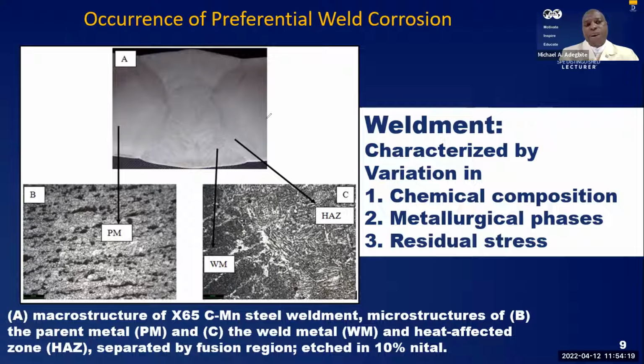You appreciate that the cooling is so sudden. Heating up a metal prior to the welding state, you're talking of a sudden increase in temperature from whatever the ambient temperature. Even when we preheat, you can imagine preheating to about 300 or 400 degrees, and now during welding, the temperature is escalated to beyond 2,000 degrees centigrade. That's a shock, a thermal shock. So such thermal shock has residual stress associated with it even in the cooling, regardless of the amount of post-weld heat treatment or the amount of controlled cooling that we can achieve, there will be a measure of residual stresses associated with the weldment. So we can see here typical morphology being shown here.